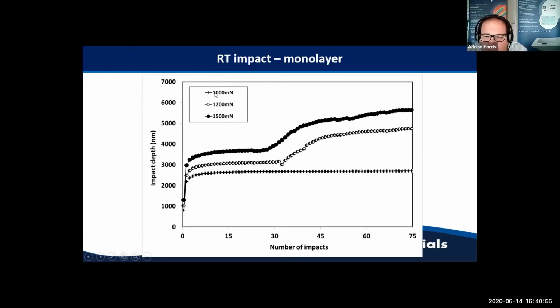So, 1 newton, 1.2 newtons, and 1.5 newtons. This is a monolayer coating, and with 1 newton, we see some initial plastic deformation on the first impact, which is absolutely inevitable, and then basically no events throughout the rest of the test duration. At 1.2 newtons, we get a bit more plastic deformation. It's inevitable because we're using a higher load, and at a certain point, we think there's something happening with the substrate material, and then the depth starts to increase. So this is a typical kind of impact failure event. Stable behavior and then an increase in the depth.